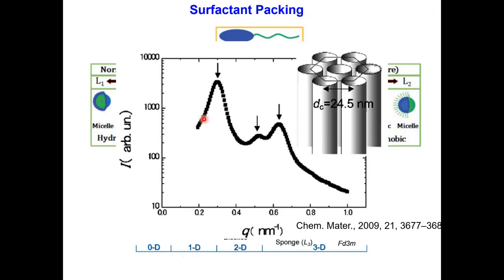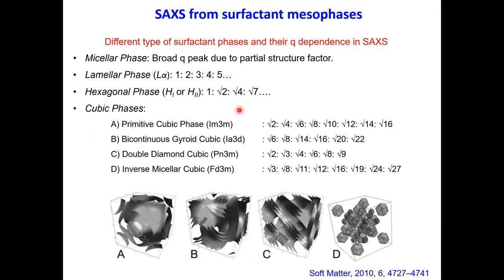These are periodic structures, and their periodicity gives rise to these sorts of peaks in small angle X-ray scattering, and these peaks appear at a certain ratio of Q values. For example, this peak is occurring at 0.28 or so, this is at 0.45, and this is at about 0.6. By looking at the ratio of the Q values, I can determine the type of surfactant packing. Here it is hexagonal, because I'll tell you the ratios in the coming slide. Yes, so here it is.